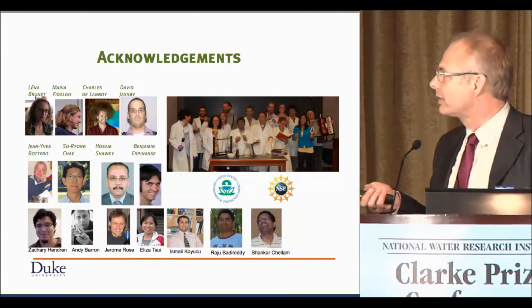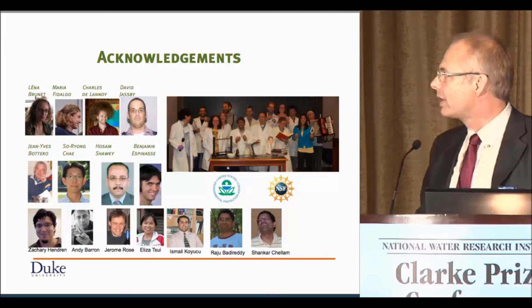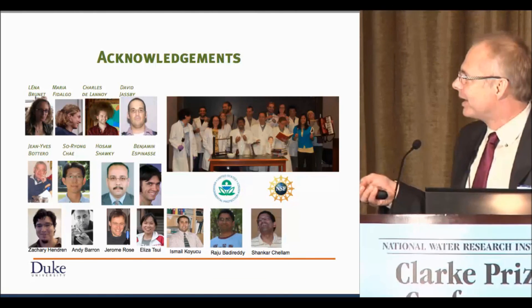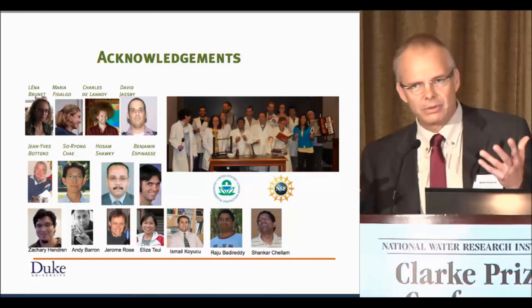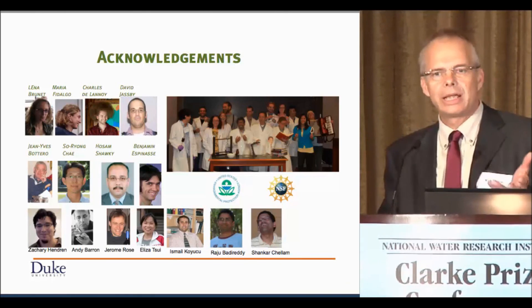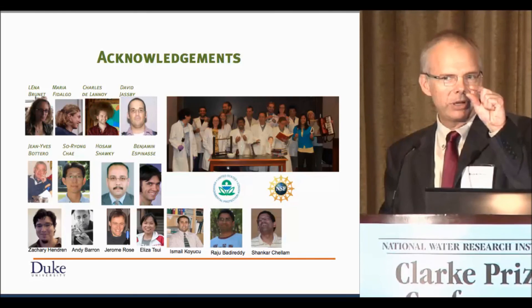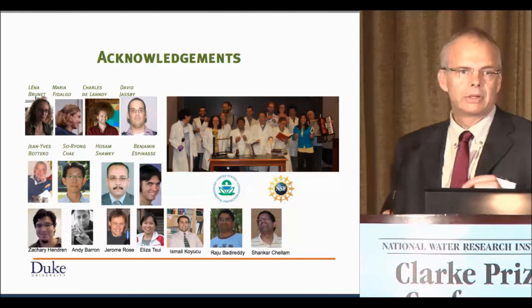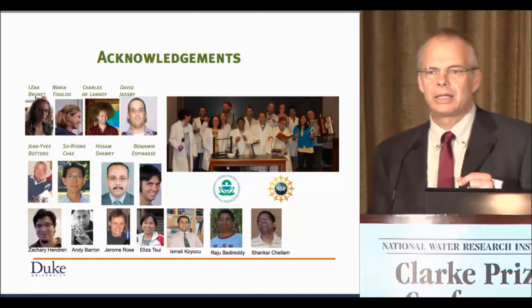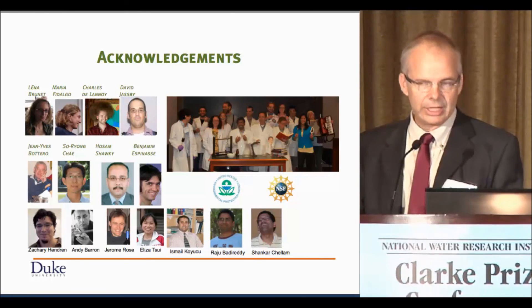The last instance I'd like to present is work that Charles has been involved in, really inspired by David Jassy, who is now an assistant professor here at Riverside. The idea was to take carbon nanotubes — using our platform for putting carbon nanotubes into polymers — and put them into a polyamide membrane. When you make the carbon nanotubes very concentrated in that polyamide composite and put that on a polyethersulfone support, you form a thin film composite. The goal was to make an electrically conductive membrane — a surface film that would carry electricity and potentially have some benefits.